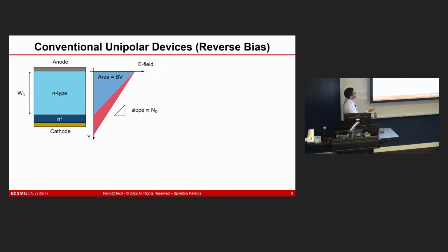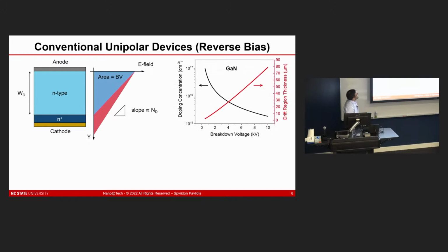So generally speaking, you lower the doping and then lower that slope as well. And the design rules that you'll see, and this is pretty generic, the numbers are tuned to GaN here, but the relationships are fundamentally the same across all semiconductors, is that as you go to a larger breakdown voltage, you've got to do a couple things. The first is that you've got to reduce your doping concentration. I already sort of alluded to that over here. And the other is that you also have to scale up your drift region thickness.